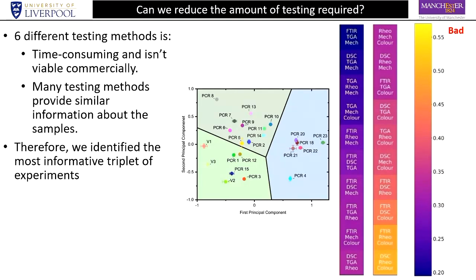So here's different combinations of 3 tests. And essentially, we look at our data set and say, if we use these 3 tests, how much do the data points move? So how much information do we lose? And really, if we've got a blue color, we lose the smallest amount of information. And if we have a yellow color here, we've lost a lot of information. So the data points have moved a lot.